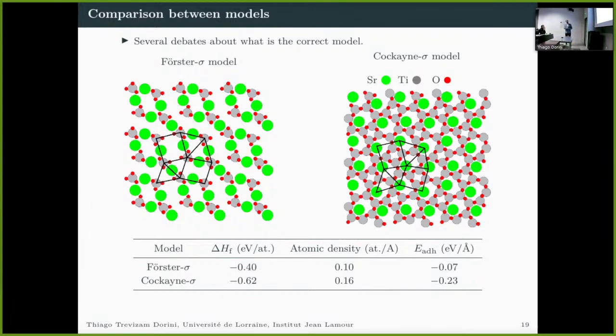So I'd like to highlight some of the characteristics of these phases. First, if you look at the enthalpy of formation for these two models, the Cockayne-σ model is a bit more stable. In addition, the atomic density, as you can clearly see, is higher on the Cockayne-σ model. This may correspond also to a decrease in the surface free energy of this phase that may lead to its stabilization. And also the adhesive energy of this Cockayne phase is stronger than on the Förster-σ model, which leads us to believe that this model may actually be the correct model to build the approximant phases.